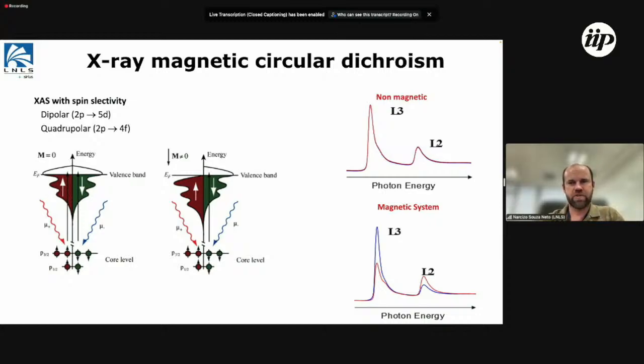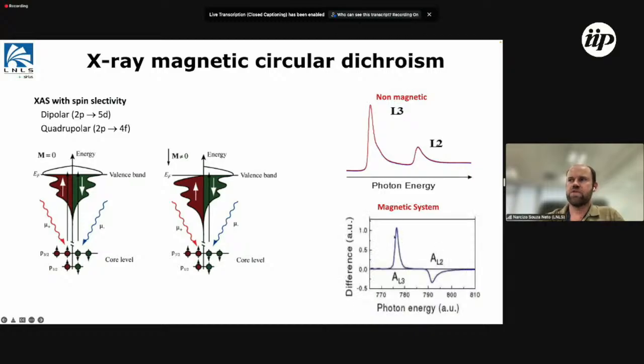the X-ray spectra, we have a difference between the L3 and L2 edge, which is due to the spin-orbit coupling, and we take the difference, we have this magnetic dichroism, which is proportional to the magnetic moment, the net magnetic moment of the material. But not only that, we are selective to the chemical element, so in a compound with five chemical elements, we can pinpoint the magnetism of only one of those.